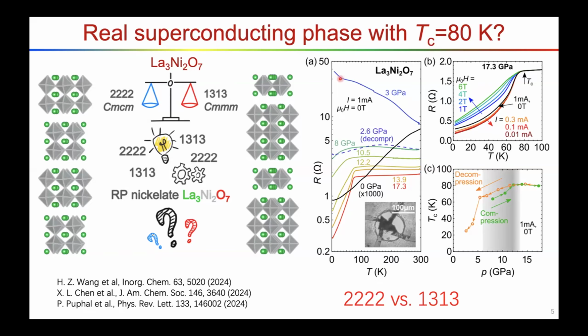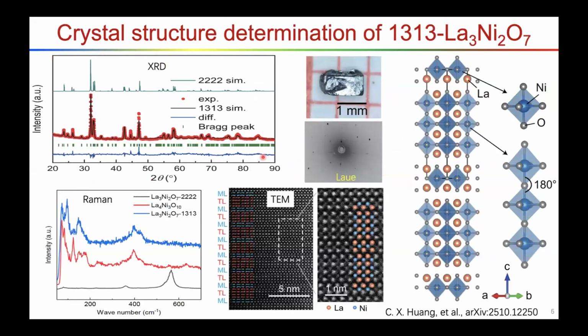But soon after this work, many other works were published, and they all demonstrate the 80 Kelvin superconductivity originates from this bilayer phase. Okay, but whether this 1313 phase is a superconducting phase, and if it is, what's the superconducting transition temperature, is an open question. So our group